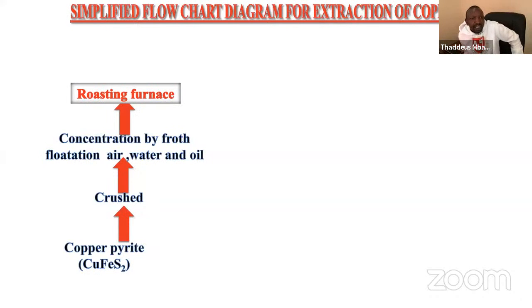Perfect. Then from there, we go to the roasting furnace. What happens in the roasting furnace? Hot air gets in. Impurities are removed, impurities such as sulfur oxide. So what reaction takes place there? Copper pyrite is roasted in air to form copper 1 sulfide, iron 2 oxide, and sulfur 4 oxide gas. Perfect. So we remember in the roasting furnace, we need hot air. So with that hot air, we have the first equation.